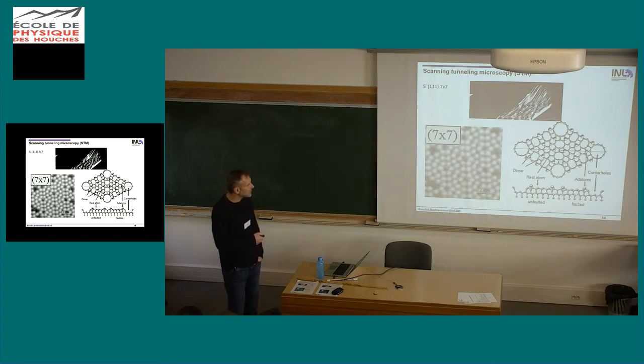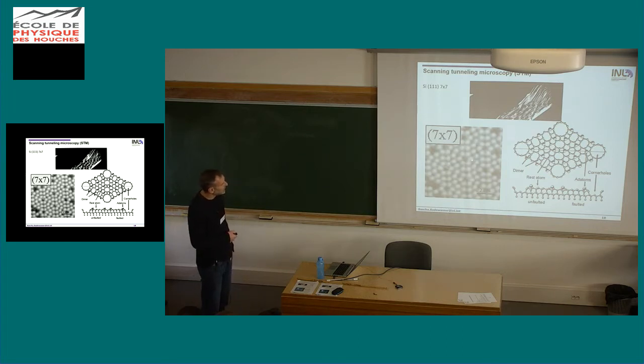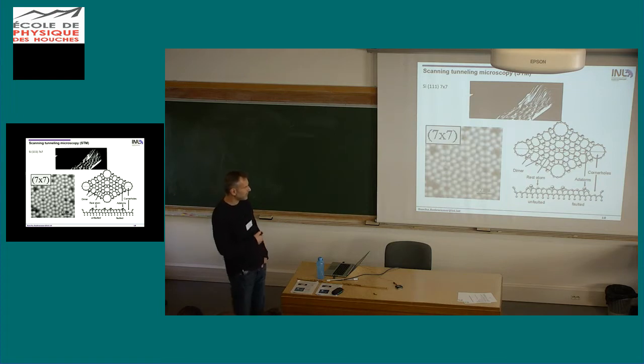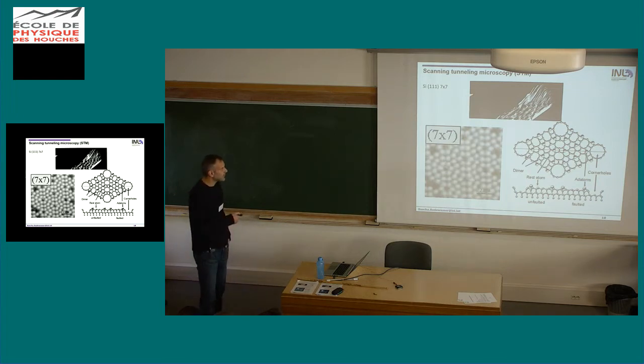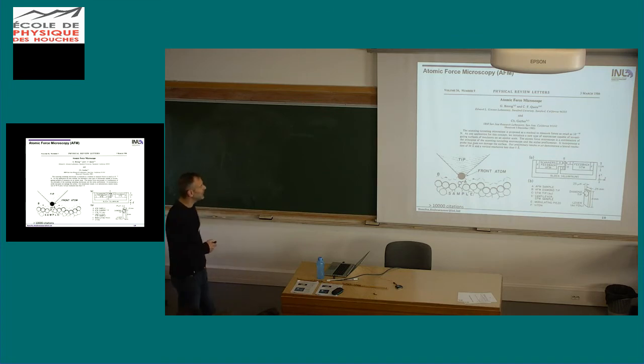And there are a lot of atoms in this surface plane. What we see in STM as these spheres here are actually the atoms. Only these atoms we see, and the other ones are slightly behind the surface. They are usually not visible here, and then you have these corner holes where atoms are missing. So it's a very complex structure, but it's a model structure. Wherever surface science is done, the 7x7 silicon 111 surface is a very famous surface. Questions so far? Good. We continue.